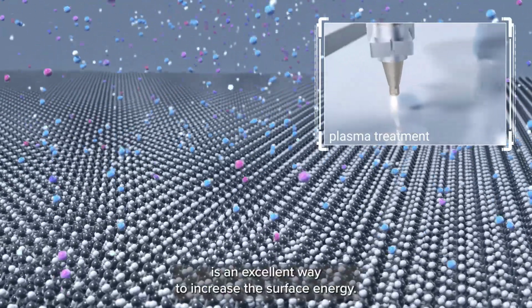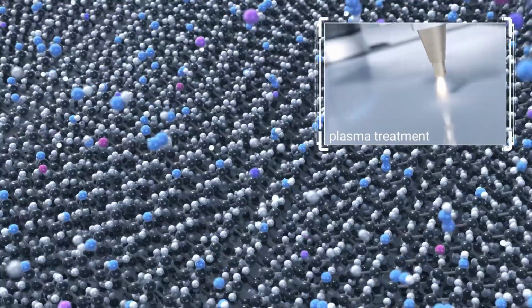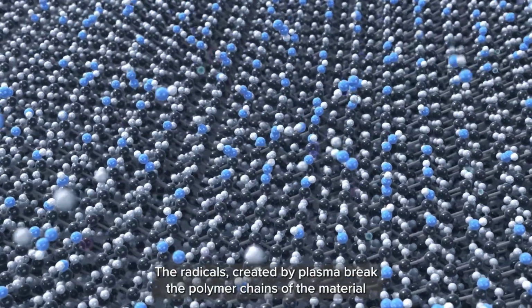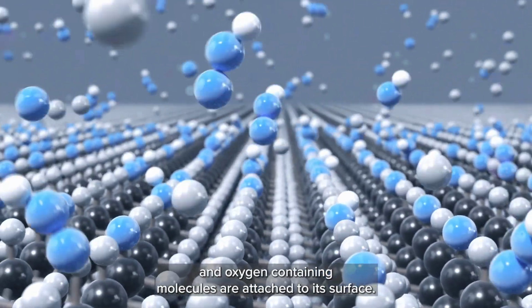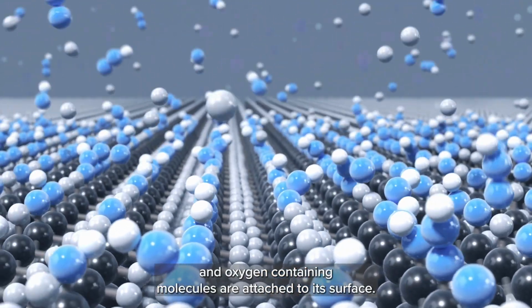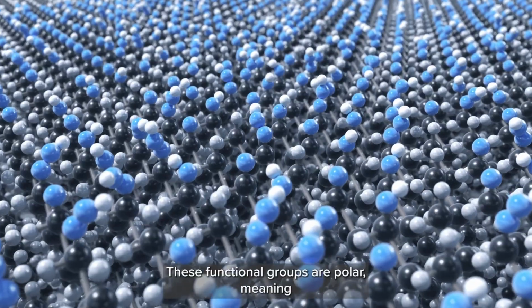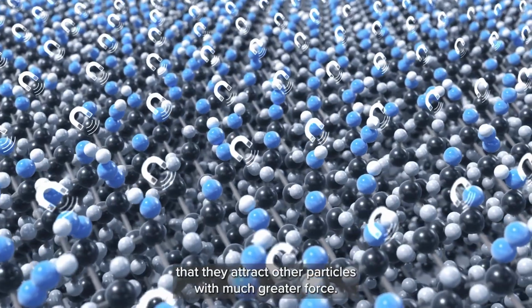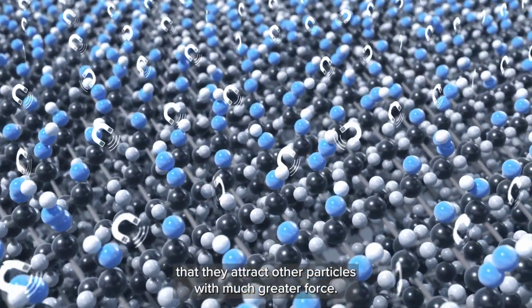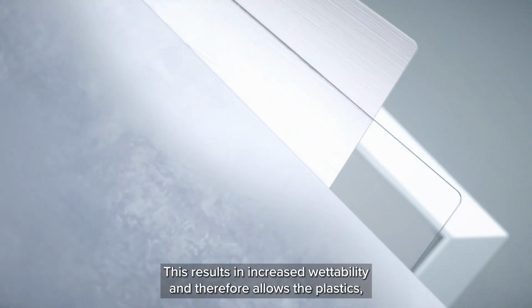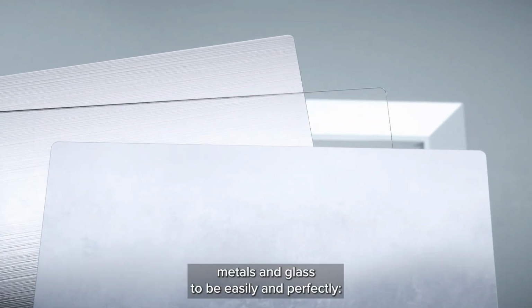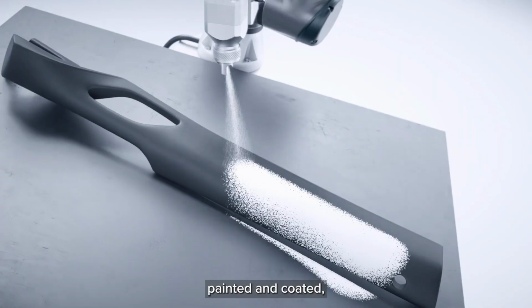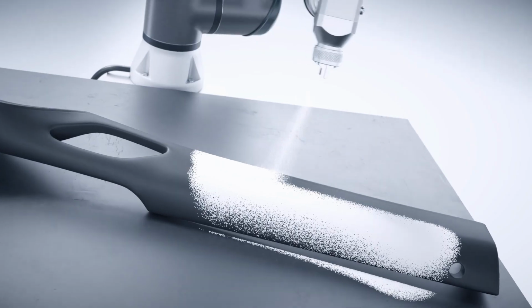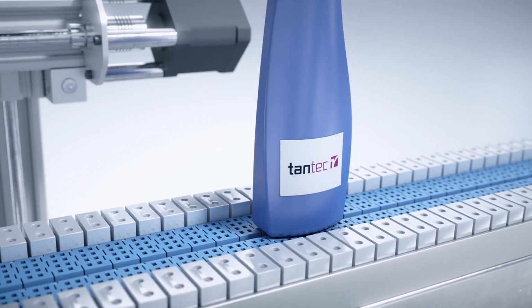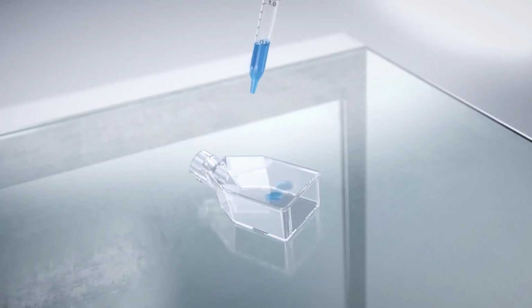Plasma treatment is an excellent way to increase the surface energy. The radicals, created by plasma, break the polymer chains of the material and oxygen-containing molecules are attached to its surface. These functional groups are polar, meaning that they attract other particles with much greater force. This results in increased wettability and therefore allows the plastics, metals, and glass to be easily and perfectly printed, painted, coated, glued, or simply wetted.